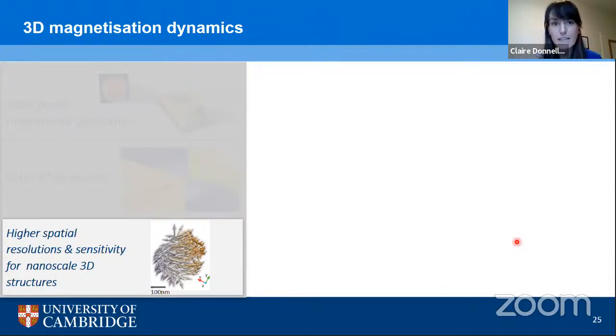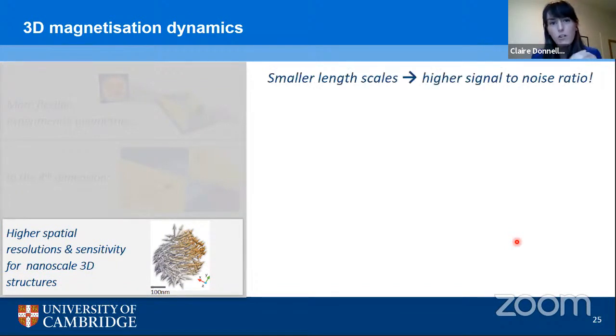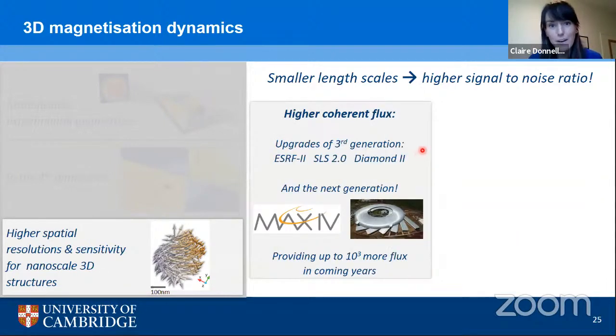And what I want to emphasize here when we're talking about these weak magnetic signals is that going to smaller length scales essentially is related to achieving a higher signal-to-noise ratio of our data set. And there's two ways in which we can improve our signal-to-noise ratio. First of all, we can go to higher coherent flux, so synchrotrons with higher coherent flux.